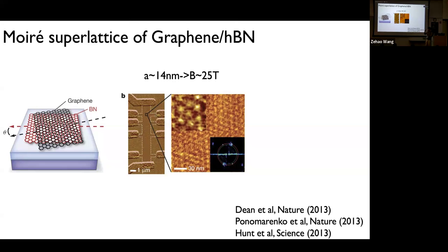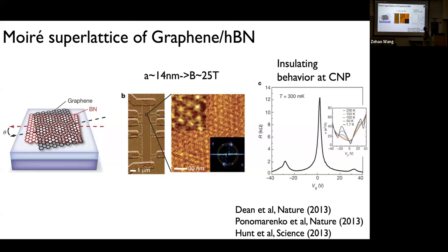If you now convert the length scale, to go to the colorful region you only need a magnetic field of the order of 25 tesla, which is achievable if you go to a National Lab high magnetic field facility. And just one comment that will become useful later, and was mentioned yesterday during Yves' lecture: the alignment to hBN for graphene will change the electronic properties of graphene, because there's what's called a mass term, a sublattice term, which will open up a gap. And indeed, in this experiment, they measured the resistance of this kind of sample and looked at the temperature dependence. And at the charge neutrality point, there was insulating behavior.